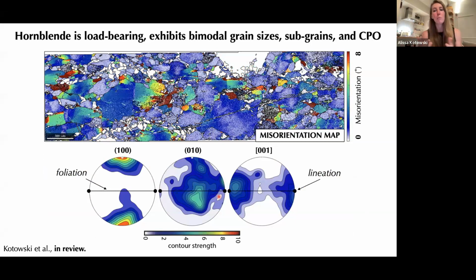So what I'm showing you now is a misorientation map. Basically, what this shows you is for every single pixel that is measured with the electron microscope, it plots the degree of misorientation of that pixel relative to the average orientation of the grain. So that's a bit of a mouthful, but all that matters is that this is basically a map showing you undulose extinction or subgrain formation. So if you've ever looked down a petrographic microscope in cross-polarized light and rotated the stage and seen sweeping undulose extinction or nice subgrains in something like quartz, this is basically exactly what that's showing you.